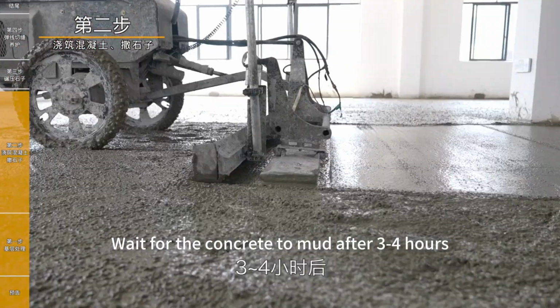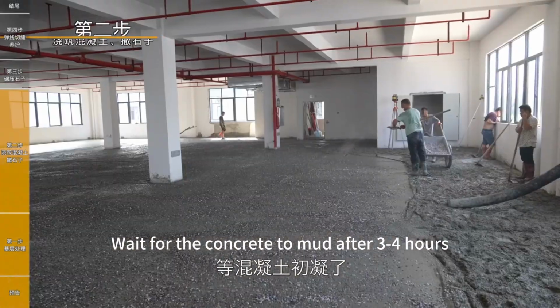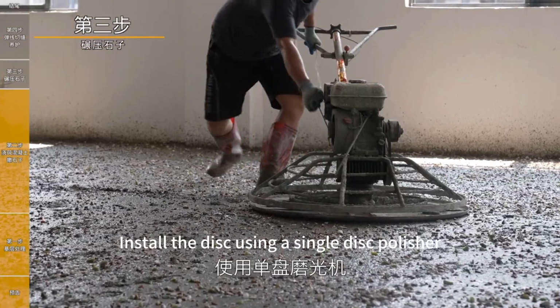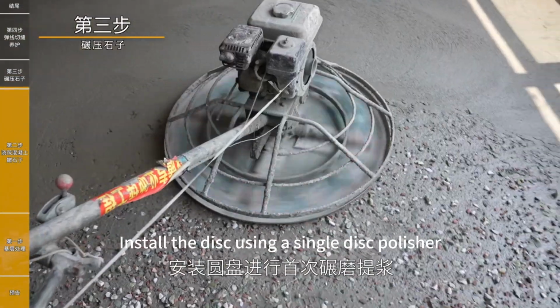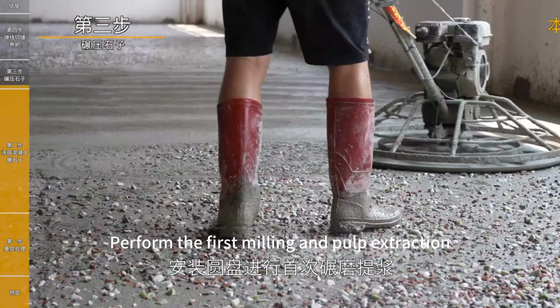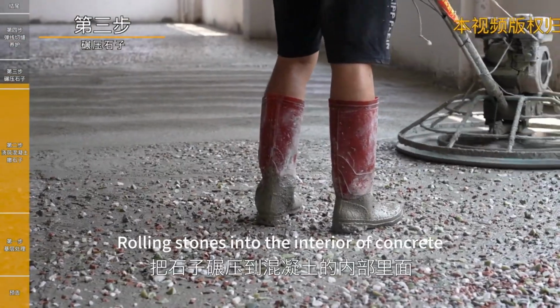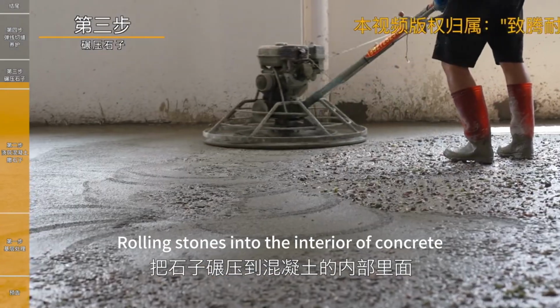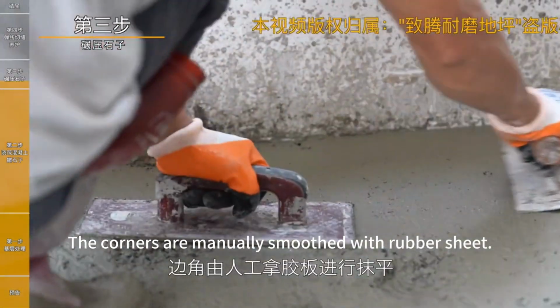Wait for the concrete to set for 3 to 4 hours. Install the disc using a single disc polisher. Perform the first milling and pulp extraction, rolling the stones into the interior of the concrete. The corners are manually smoothed with a rubber sheet.